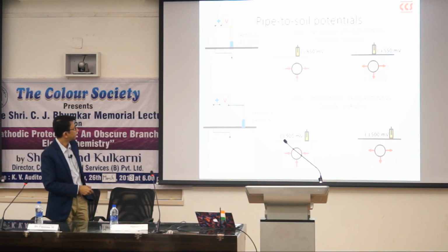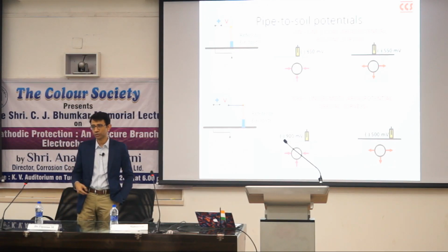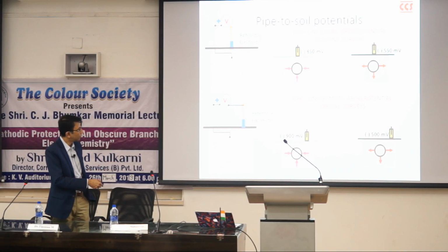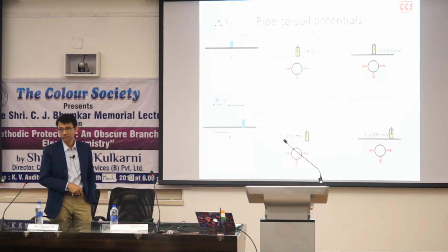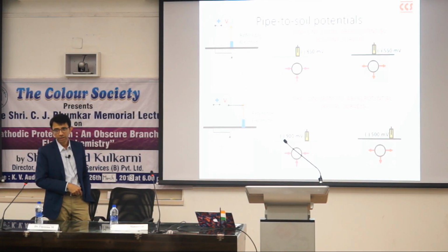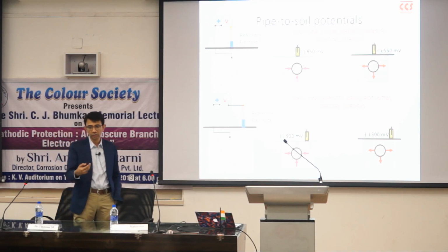Similarly, we find in this slide, although this is more for instruction, but it's interesting, when you place a reference electrode directly over the structure, you get a certain potential. When you move laterally away, you actually measure a greater potential because you have a higher resistive drop in the soil, right? Because every soil has resistance, the coating has resistance, and you have current in the circuit. So you have current times resistance, which is an IR or a voltage drop.